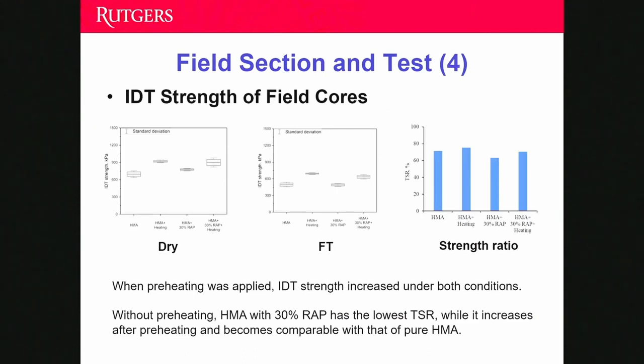And here is the results of the IDT strength of field cores. We found that the IDT strength increased under both dry and freeze-thaw conditioning if we applied preheating. This actually verifies the positive effect of the preheating method. And from strength ratio point of view, although the HMA with 30% wrap has the lowest tensile strength ratio, which means the poor moisture sensitivity, however, when we apply the preheating, the tensile strength ratio increased and becomes comparable with that of the pure HMA.